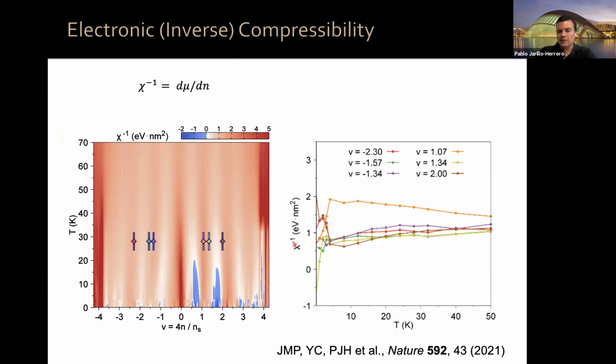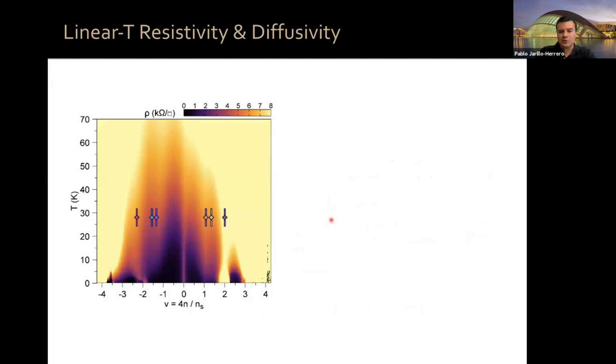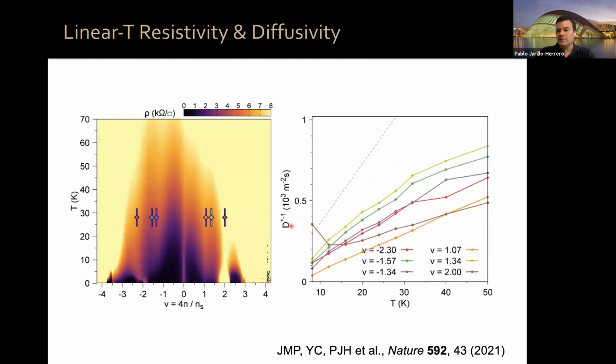Okay, so you can see this is the inverse compressibility as a function of temperature, and you can see that it's relatively weakly temperature dependent. Then I can put these two together and measure the inverse diffusivity. In this case, just to give you some details, it's a D star, so I'm subtracting the offset in the resistivity. By putting together resistivity data and the inverse compressibility data, we have the inverse diffusivity. And as you can see, the major contribution to the linear resistivity in temperature comes from the linear behavior in temperature of the inverse diffusivity. The compressibility has a relatively weak temperature dependence.